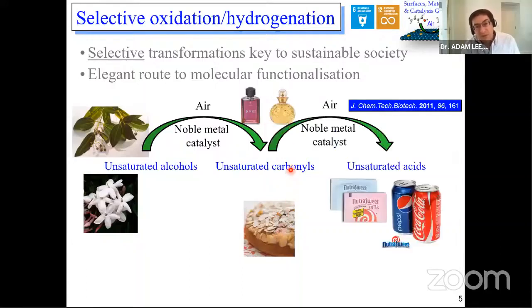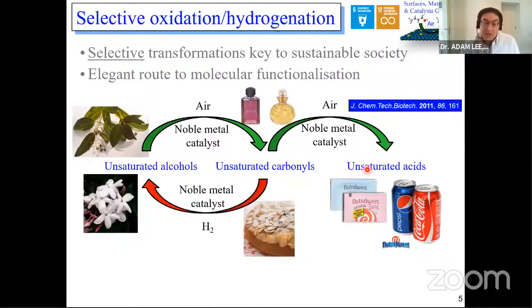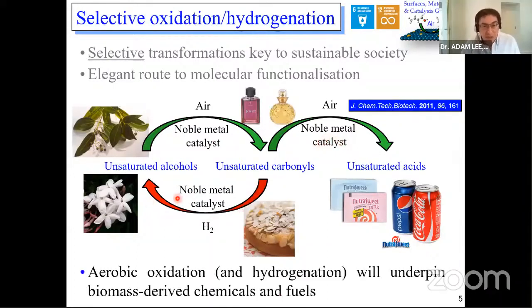And you can even oxidize it further to make the corresponding cinnamic acid, which is a precursor to aspartame, so an artificial sweetener. And in general, of course, reactions that you can do by oxidation, the same catalysts are often effective at doing the corresponding reductions. So we'd like to try and make these cascade reactions using oxidation and hydrogenation catalysts, which will allow us to take biomass and produce a range of important chemicals and fuels from them.